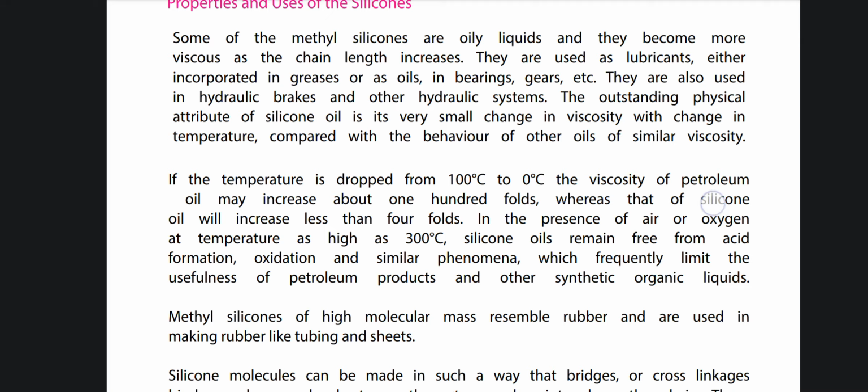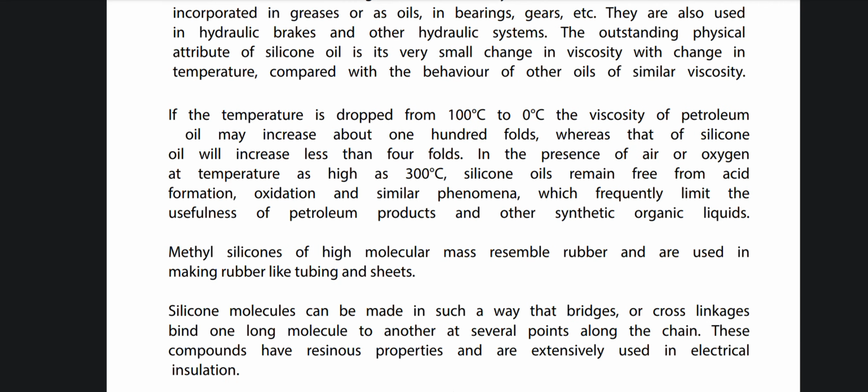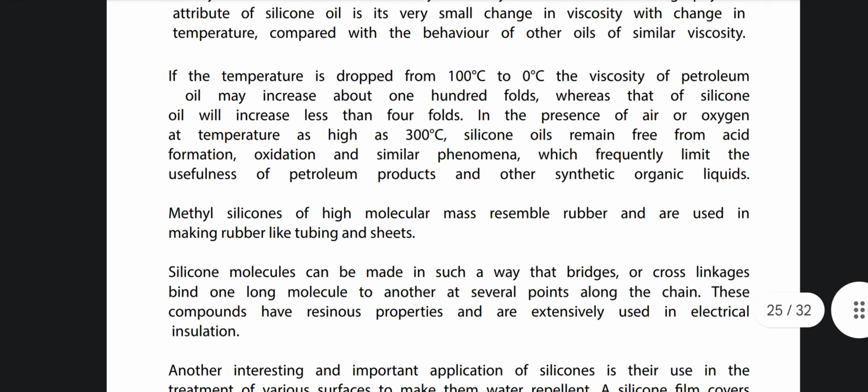If the temperature is dropped from 100 degrees Celsius to 0 degrees Celsius, the viscosity of petroleum oil may increase about 100 fold, whereas that of silicone oil will increase less than 4 fold. In the presence of air or oxygen at temperatures as high as 300 degrees Celsius, silicone oils remain free from acid formation, oxidation and similar phenomena which frequently limit the usefulness of petroleum products and other synthetic organic liquids.